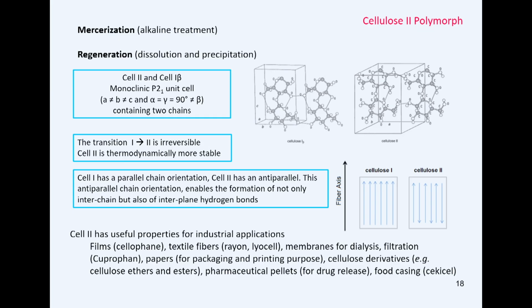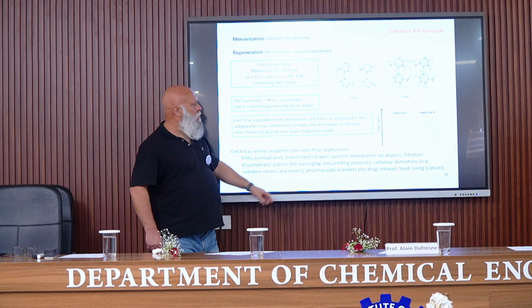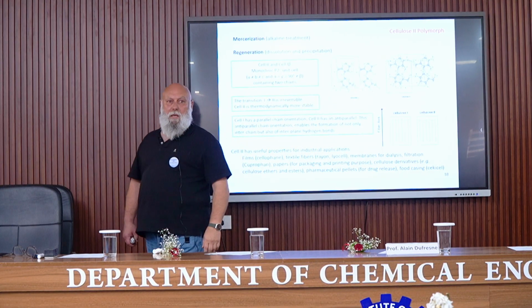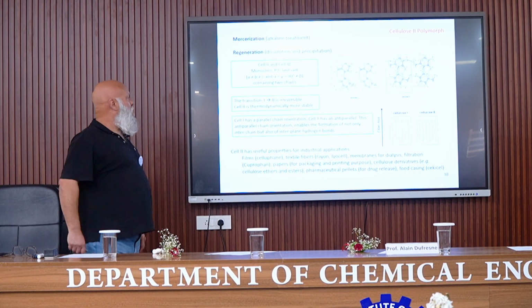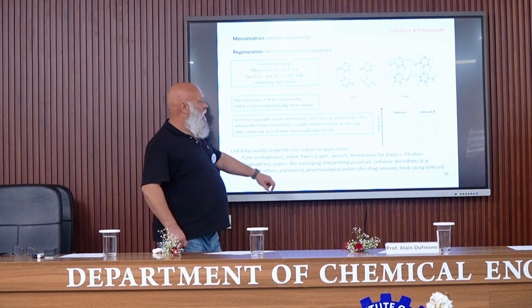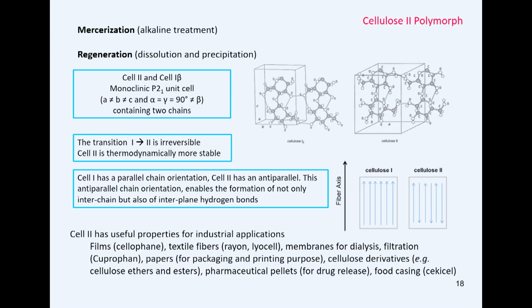So this is some description about cellulose 2. I mentioned previously that the transition 1 to 2 is irreversible. What is important in terms of difference between these two crystalline forms is the orientation of the macromolecule. Remember that cellulose chains have a reducing and a non-reducing end. Cellulose 1 has a parallel chain orientation, meaning that all reducing ends are on the same side in the cellulose fiber. Cellulose 2 has an anti-parallel organization.